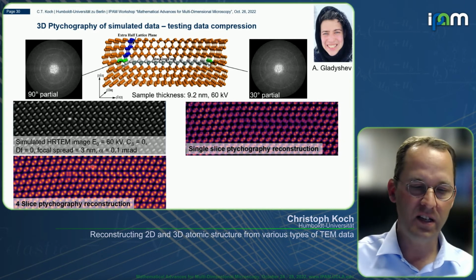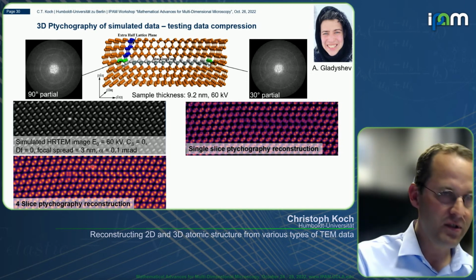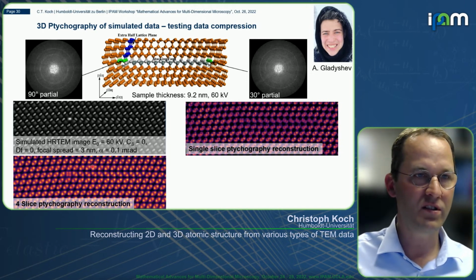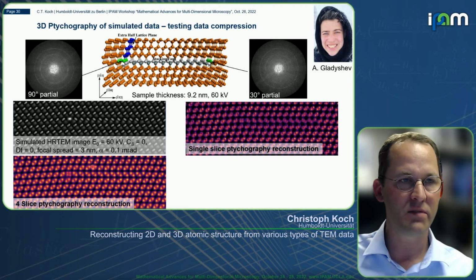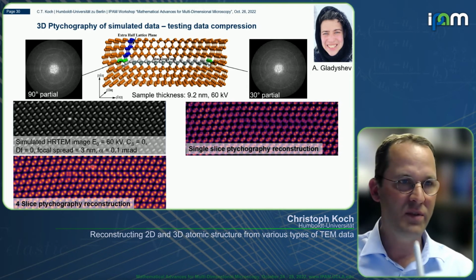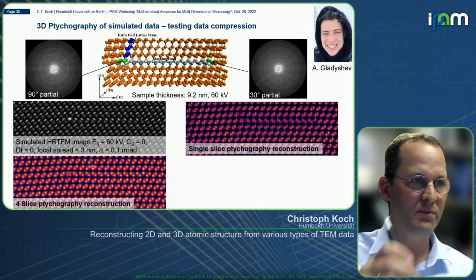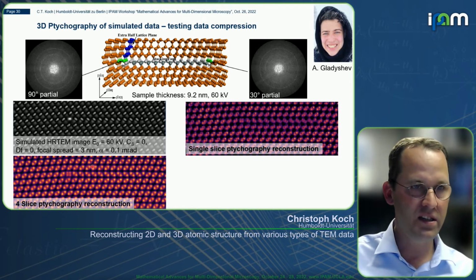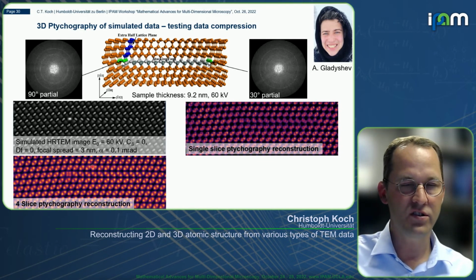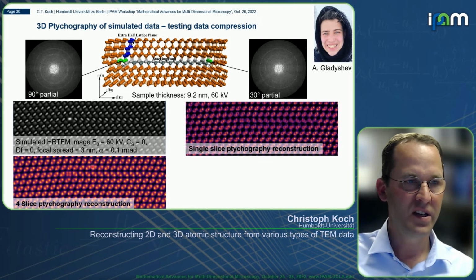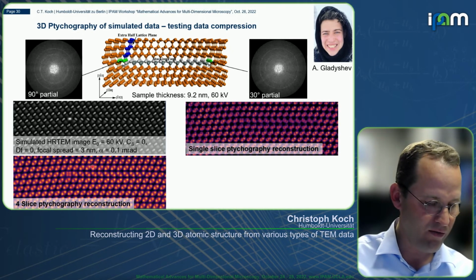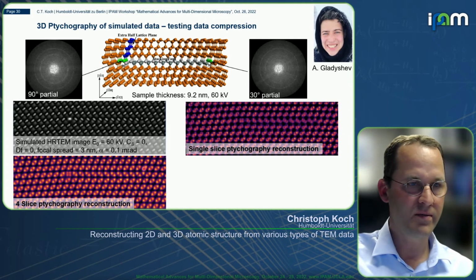And of course, if you then use multiple slices in the reconstruction, you get a faithful representation of the atomic positions. Interestingly, the beam was only positioned every 1 angstrom. So in contrast to many of the ptychographic experiments where the beam is positioned much more finely, for example, 0.2 angstroms or so, here in the simulation it was only positioned every 1 angstrom. And that was barely enough to resolve, in principle, in an image, the distance between these 2 silicon columns here.